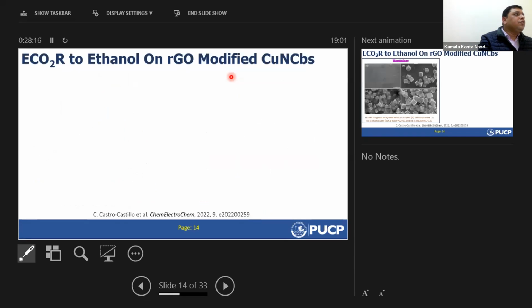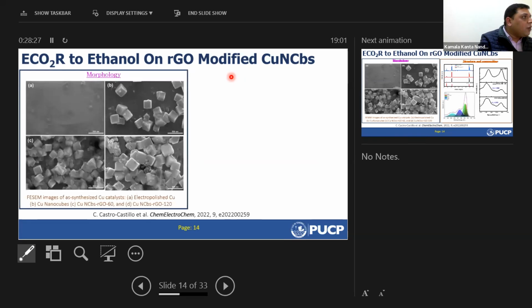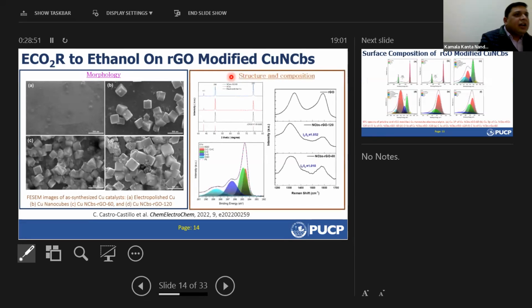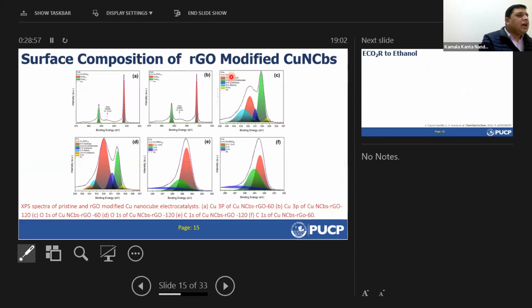So what we did is we went to the literature and found that carbon nanomaterial can convert carbon dioxide to carbon monoxide. So we adopted a standard electrocatalysis technique, but we designed copper nanocubes on the copper electrode surface and modified them with graphene, reduced graphene oxide. We also increased the thickness of the reduced graphene oxide layer to see the effect of the thickness of the graphene oxide layer on C2+ product selectivity and ethanol selectivity. And we confirmed the presence of the graphene layer by Raman spectroscopy and XPS spectroscopy.